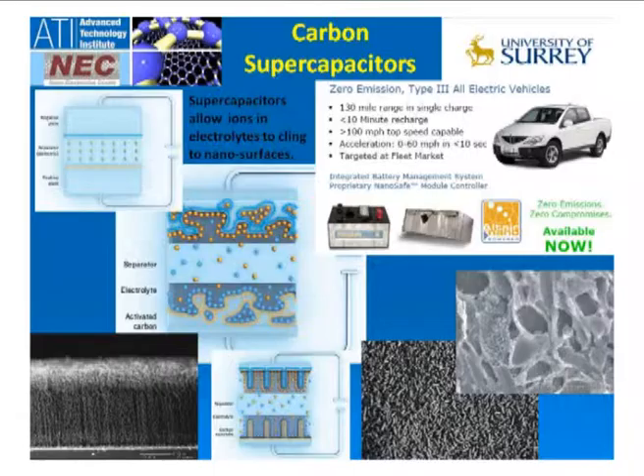Another area where nanotechnology is extremely important in the energy issue is supercapacitors. The material mostly used currently is activated carbon — carbons that are heated up to about 1,300 to 1,500 degrees in super-saturated environments of water. That creates nanopores allowing surface areas of the order of 3,000 square meters per gram of material, giving much, much better storage.